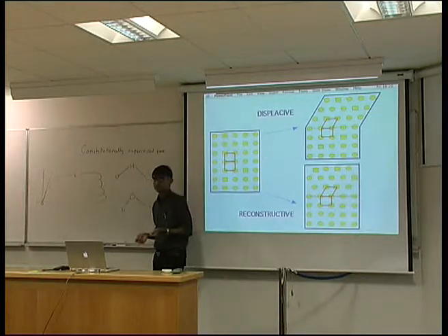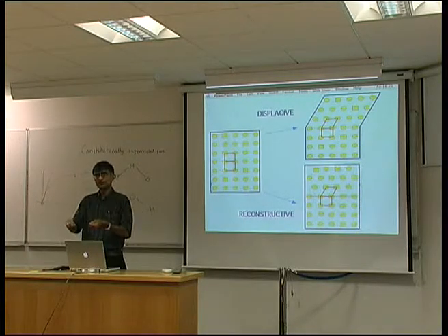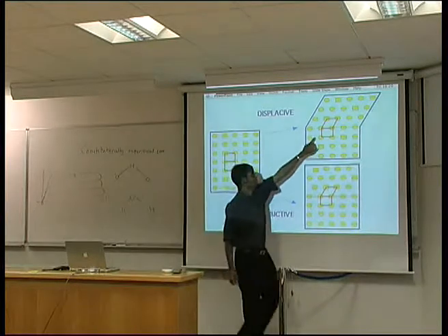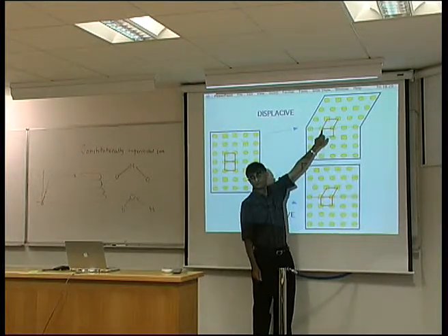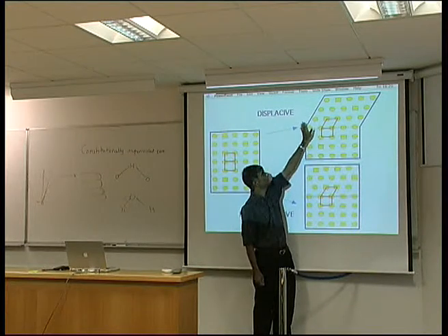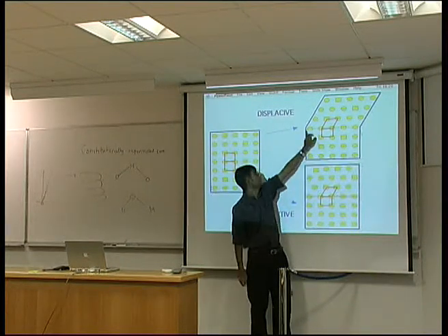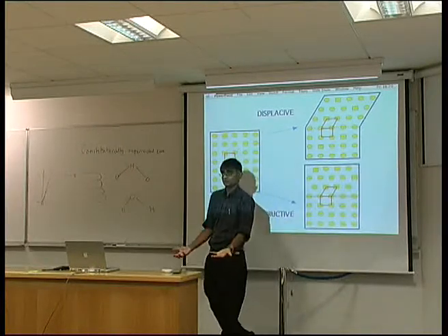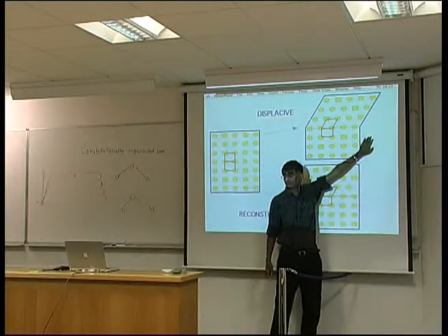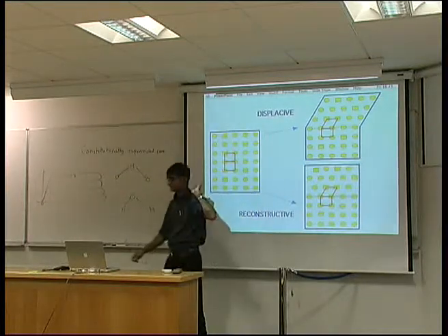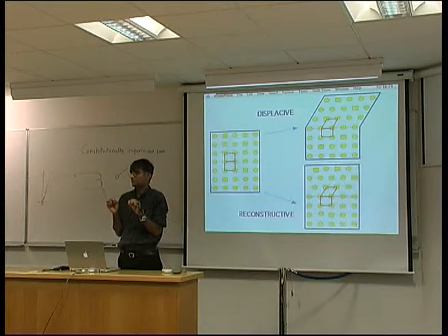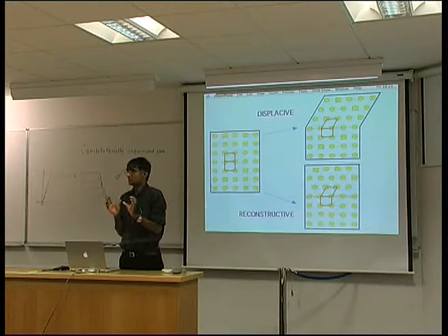But there is another way of changing the crystal structure, and that is by physically deforming it into a different pattern. So here we have this unit cell, and it's deformed into a different pattern. And of course, if the arrangement of atoms changes without diffusion, then the whole shape of the crystal will also change. So imagine that this is happening inside a bulk of material, a solid lump of material. It's going to cause a lot of strain because there's material surrounding this. So this is a case where the transformation is dominated by strain energy. And the product phase will form in a way which minimizes the strain energy. So the shape is determined by strain energy.